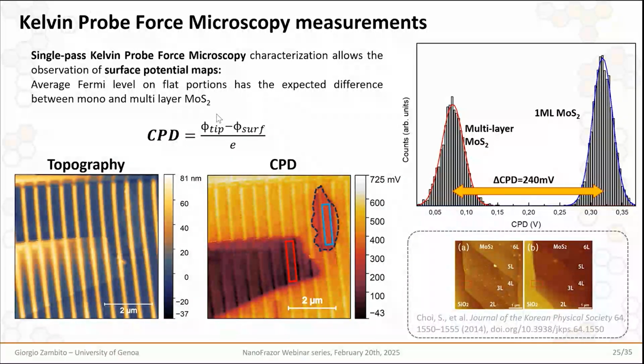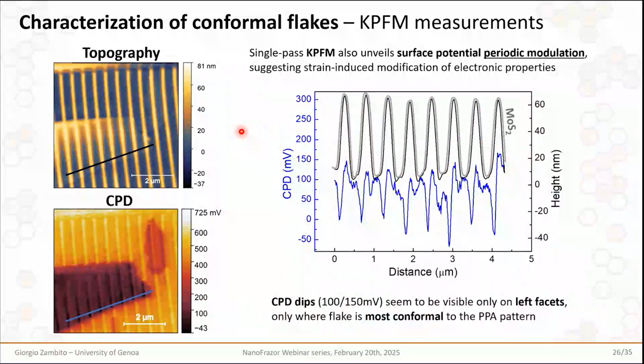So to try and understand if there is some kind of localized effect at a high resolution on the electronic properties of the flakes due to the underlying pattern, we started extracting CPD and topography line profiles from the two images. And we started observing that there is actually a periodic modulation of the work function of the flake. We observed that this periodic modulation has the same periodicity as the underlying pattern, and also we have CPD dips, or we can say increases of work function, that are localized in certain positions. And we notice that they are localized not on the top of the ridges, not in the valleys, but on left facets.